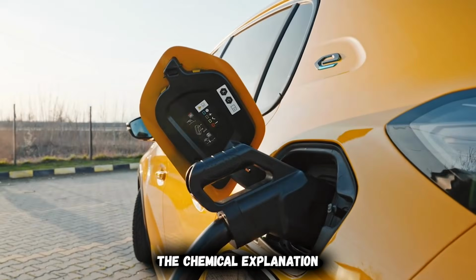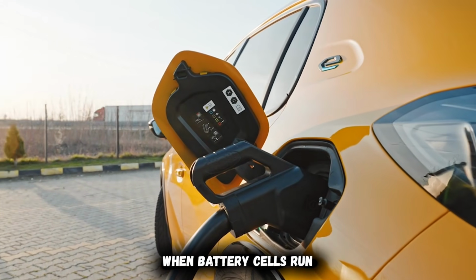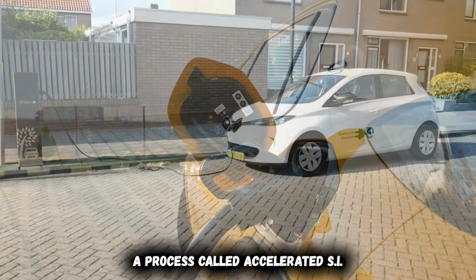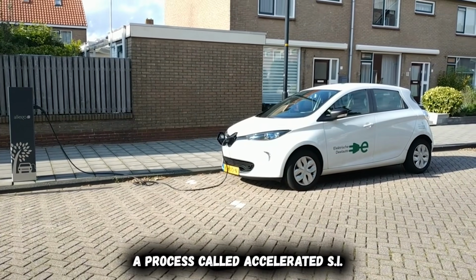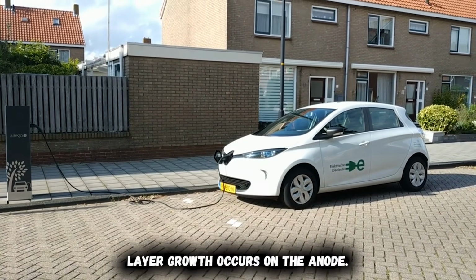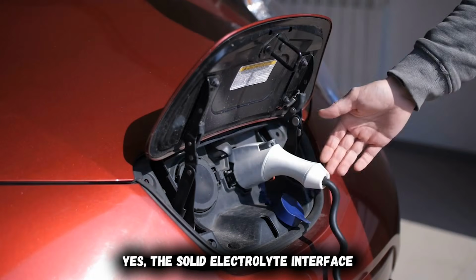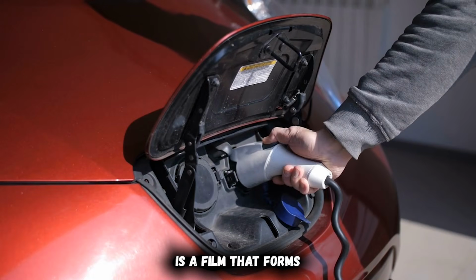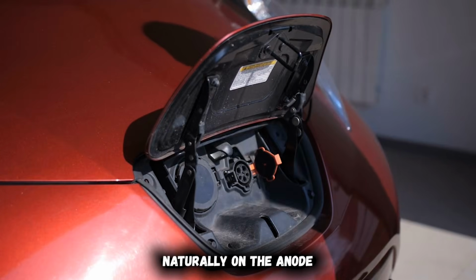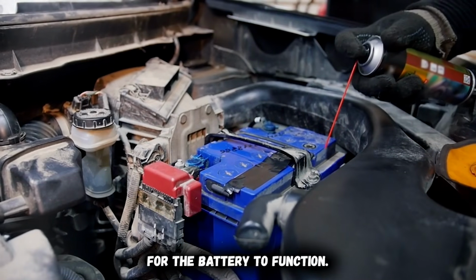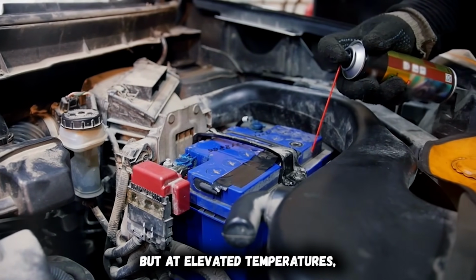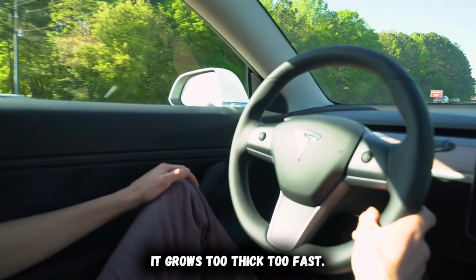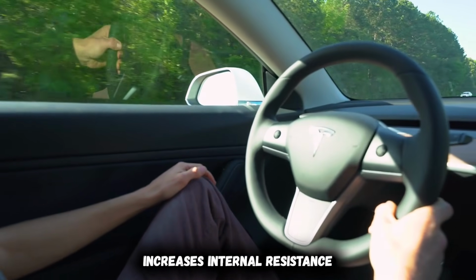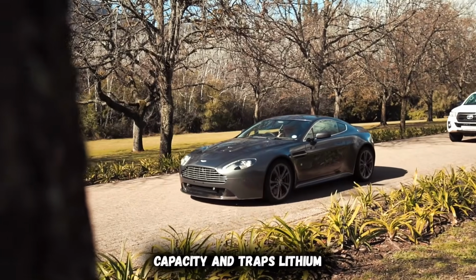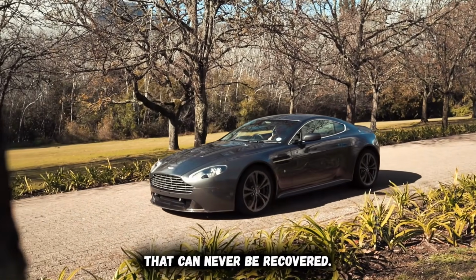The chemical explanation is important here. When battery cells run hot consistently, a process called accelerated SEI layer growth occurs on the anode. The SEI, solid electrolyte interphase, is a film that forms naturally on the anode and is actually necessary for the battery to function. But at elevated temperatures, it grows too thick too fast. That thick SEI layer increases internal resistance, permanently reduces capacity, and traps lithium that can never be recovered.